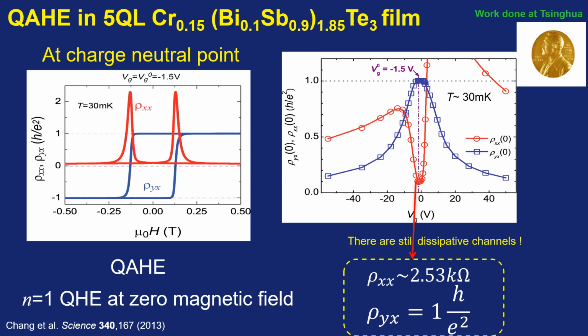If we plot the zero magnetic field Hall resistance and longitudinal resistance as a function of gate voltage, we can see the Hall resistance is quantized here. There is a plateau. At the same time, the longitudinal resistance shows a sharp dip. So this phenomenon marks the observation of the quantum anomalous Hall effect. And our work was also featured in the scientific background of the 2016 Nobel Physics Prize to demonstrate the great contribution of Duncan Haldane.